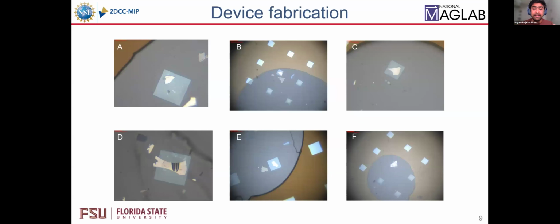These are the different stacks that I made. We can see pictures A to F, the materials that I successively transferred to the LTEM grid with a graphene top layer. The main challenge was that after transferring, I needed to wash off the excess polymer. You can see there is a gray-colored polymer residue, so I have to wash this off using chloroform.